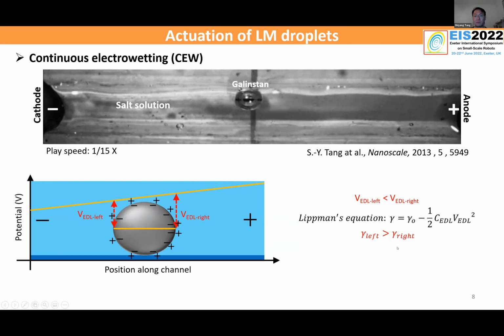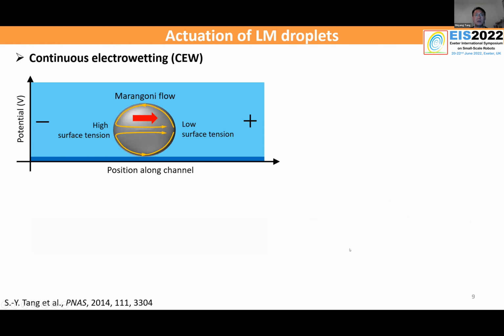So in this case, the interfacial tension on the left-hand side is going to be higher than the interfacial tension on the right-hand side. By applying an external potential gradient, I'm generating a gradient of interfacial tension along the surface. The consequence of the gradient of interfacial tension is called the Marangoni effect. It's going to pull the liquid from the low surface tension area towards the high surface tension area. So the surface of the droplet will act like a conveyor belt, which is going to drive the droplet itself towards the anode.